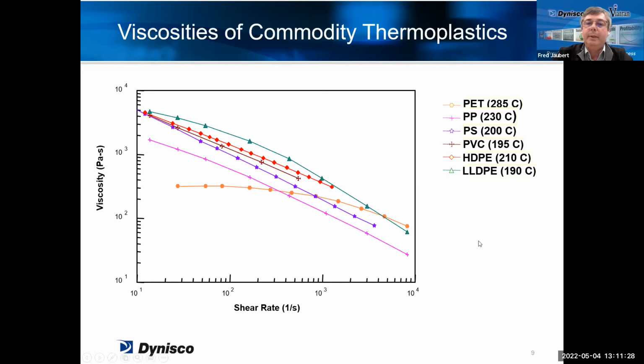When you are running plastics, I would say, not elastomers, usually we are running the test by starting with a fast speed first and then going down to the lower speed. If we are running elastomers, usually we do it the other way around. So we start with the first points, which are here, and going down in viscosity.